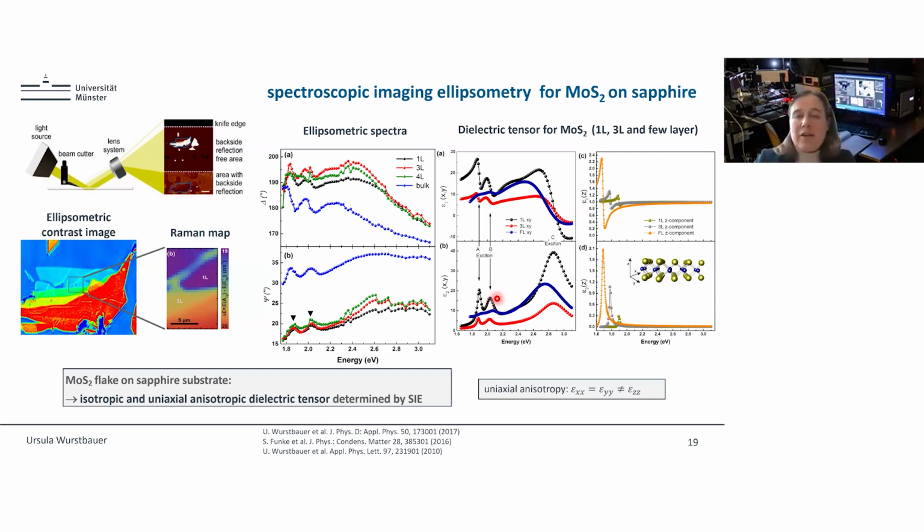We see also that we have higher transitions. If you look very carefully, you see here also a little edge or a glitch. This is then the single particle transition. But most stunning was that we indeed could also observe some contribution in Z direction, so meaning out of plane, even for the monolayer. That's a very tiny contribution, which increases with the number of layers, and which is also redshifted as expected with increasing number of layers.